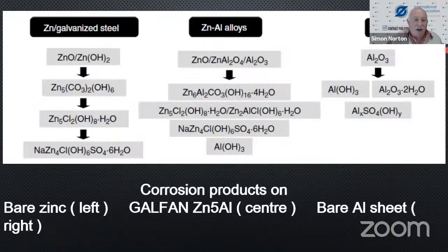If you have a look at this diagram, you'll see on the left-hand side the corrosion products of zinc when exposed to the atmosphere, in an unprotected marine atmosphere. So if you look at the galvanized steel, you can see immediately there's zinc oxide and then all the products that form. If you had Galfan, which is a mixture of zinc and 5% aluminium, you get a different structure. And if you had an aluminium structure, you'll see that on the right.